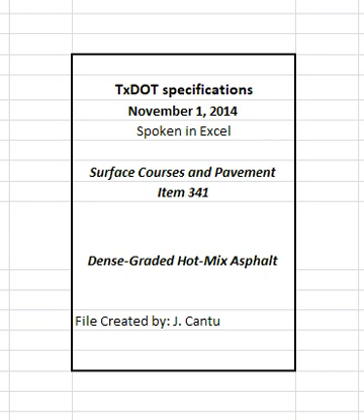4.5.1 Storage and heating of materials. Do not heat the asphalt binder above the temperatures specified in Item 300, asphalts, oils, and emulsions, or outside the manufacturer's recommended values. Provide the engineer with daily records of asphalt binder and hot mix asphalt discharge temperatures, in legible and discernible increments, in accordance with Item 320, Equipment for asphalt concrete pavement, unless otherwise directed. Do not store mixture for a period long enough to affect the quality of the mixture, nor in any case longer than 12 hr unless otherwise approved.